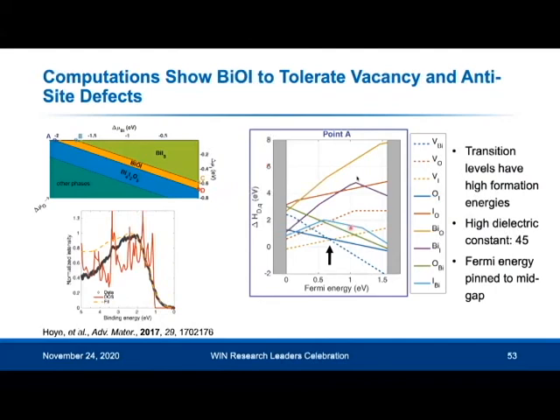And in this diagram, 0 eV Fermi energy represents the valence band maximum, this represents the conduction band minimum, and this white space represents the band gap. And these different lines here represent different defects. For example, this dashed line is a bismuth vacancy.